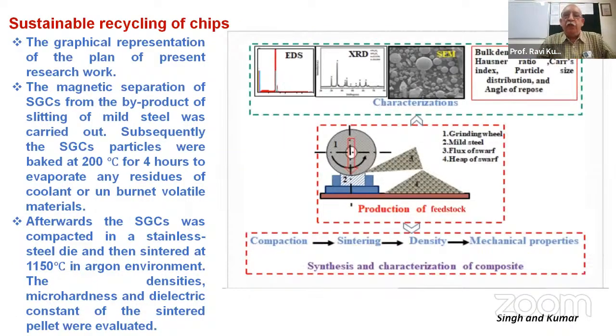Here you can see we can have a production of this material, and then we collect it. I can show you the graphical representation of the plan of the present research work. The magnetic separation of the SGC from the byproduct of slitting of mild steel was carried out. Subsequently, SGC particles were baked at 200 degrees Celsius for 4 hours to evaporate any residual coolant or unburnt volatile material. Afterward, the SGC was compacted in a stainless steel die and then sintered at very high temperature in an argon environment. The densities, micro hardness, and dielectric constant of these materials we are studying.